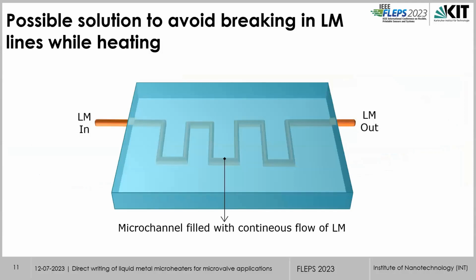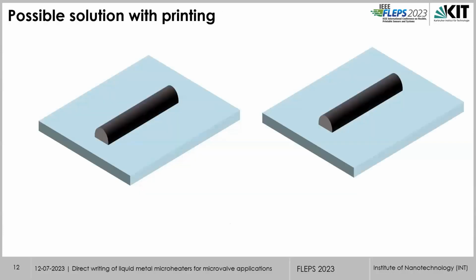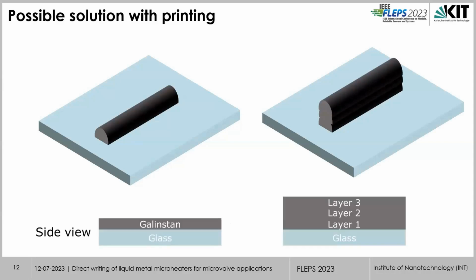A possible solution is to use a microchannel, put liquid metal on one side, and keep the liquid metal flowing into the circuit while heating. But here again there is complexity, like fabricating microfluidic channels, the constant supply of liquid metals, and maybe wastage of liquid metal. With direct writing, as a possible solution, if we increase the height of the liquid metal lines, it makes these structures more stable than single lines, and it also reduces the complexity of the other solutions.